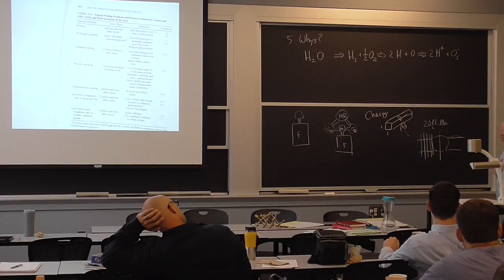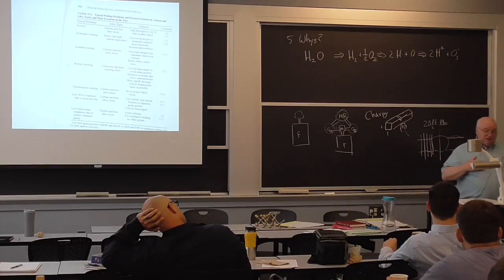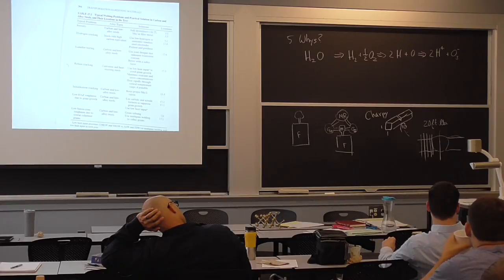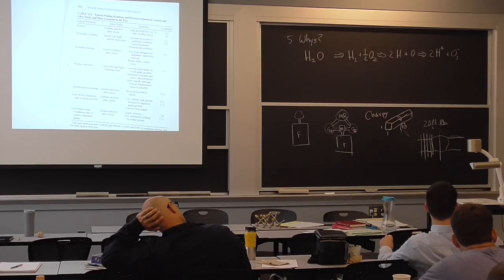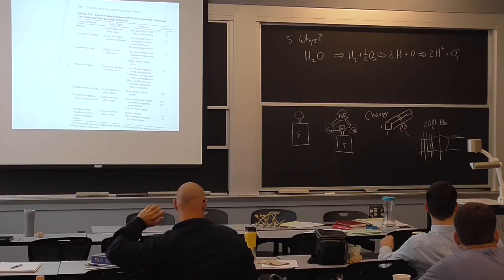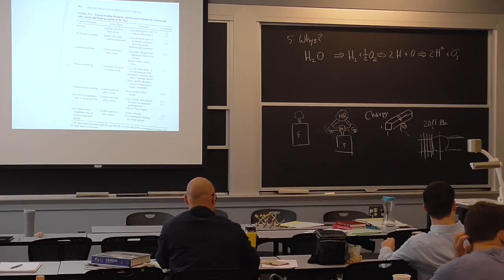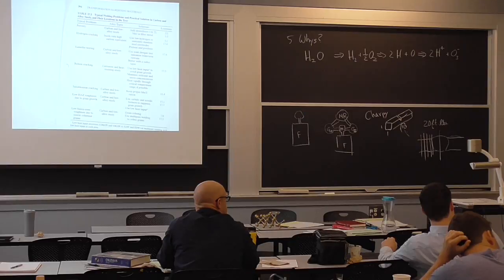Well, it turns out there was variability in the steel plate, and it turns out Bethlehem Steel, at that time, the base metal would meet 20 foot-pounds 70% of the time when it came out of the mill, first pass. Well, you didn't want to scrap 30% of your steel, so what would they do? They would send it back through the heat treatment furnace. In this case, it's a normalization furnace, where you just heat it up to upper critical and you slowly cool it, and you get a finer grain size, and it should give you better toughness. So they would do a reheat or normalization heat treatment, okay, to try to improve the toughness.